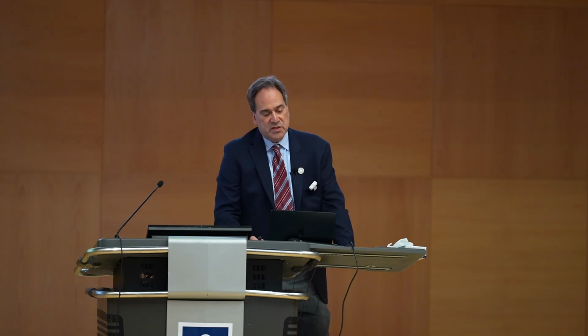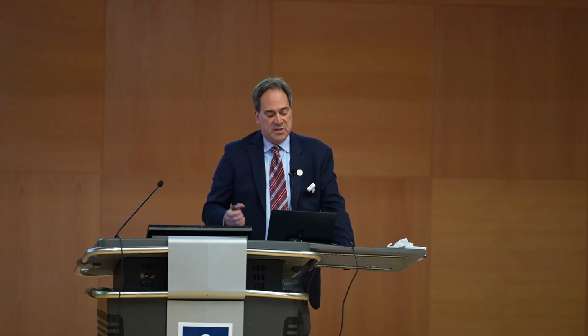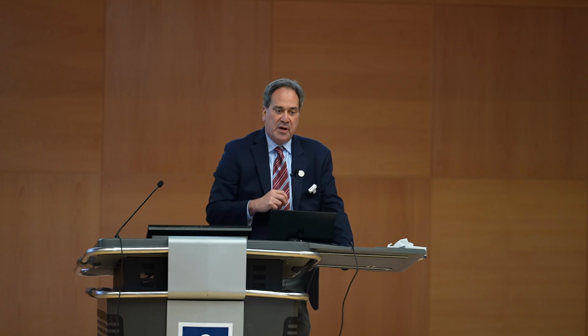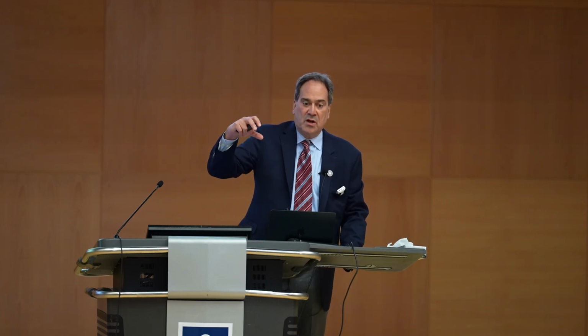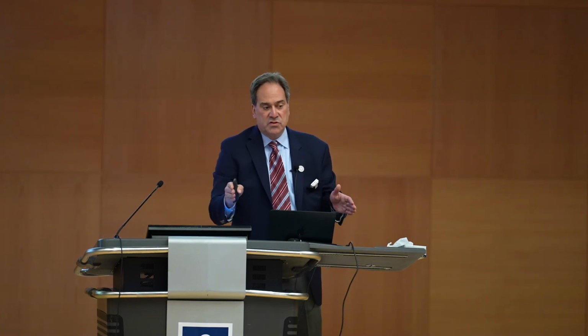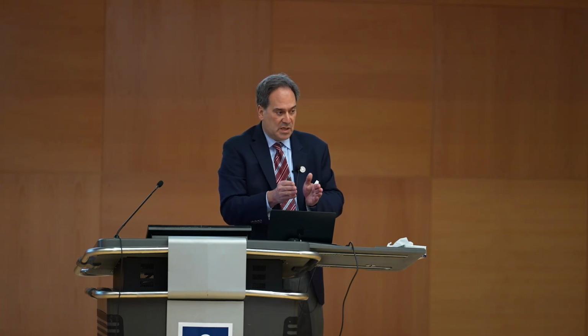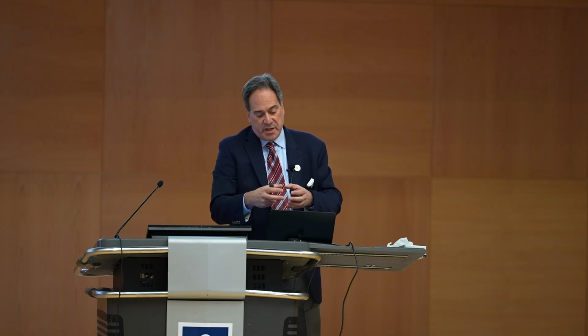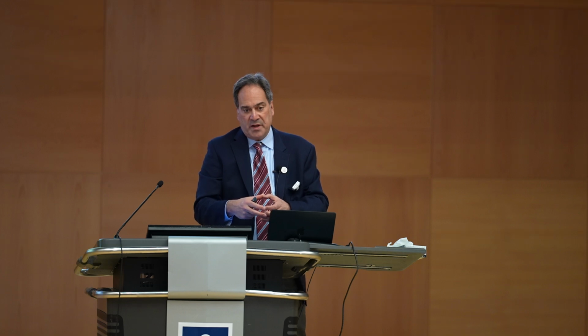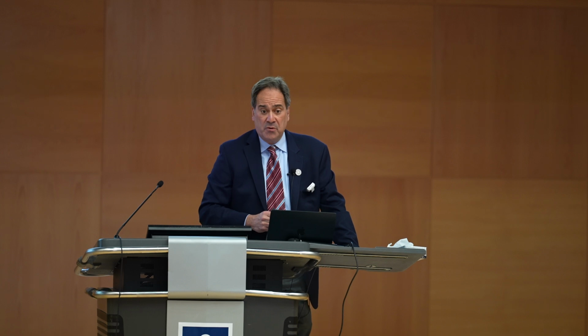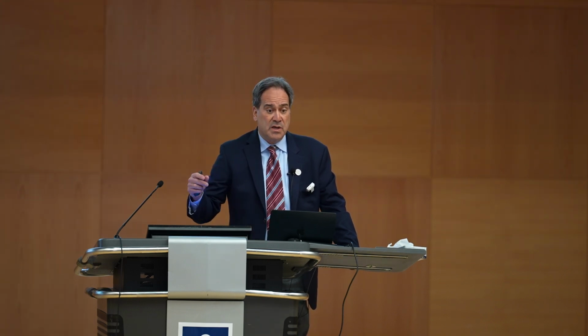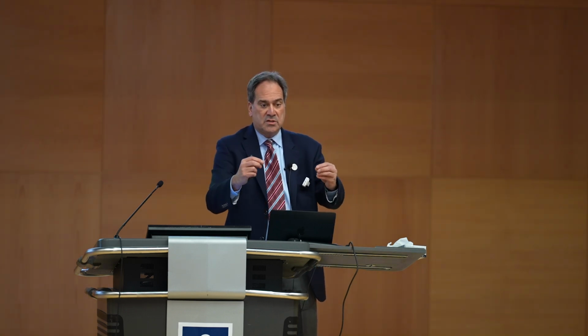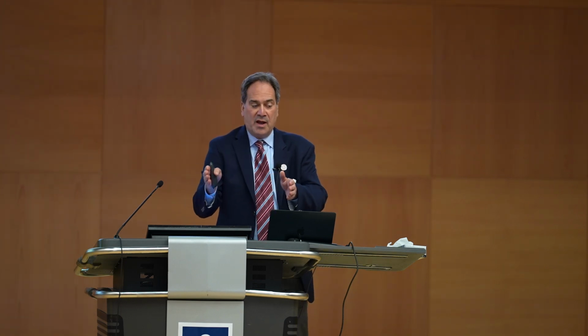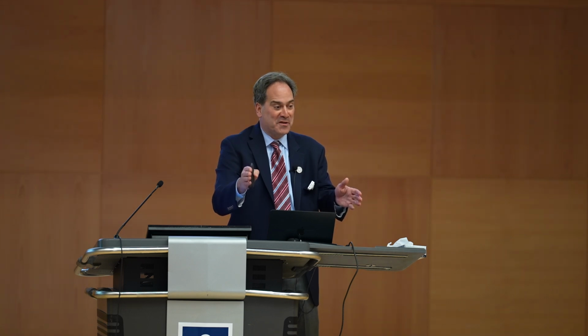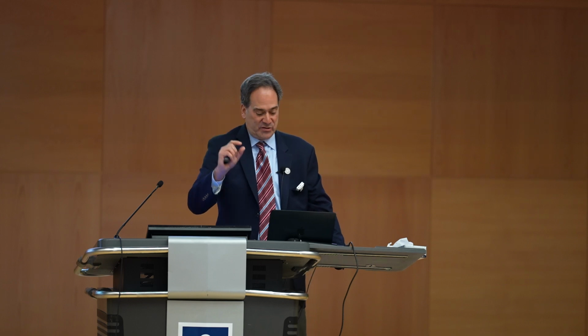So we came along and we said we could use these tools, these scanning probe tools, and block copolymers, in this case polyethylene oxide-poly-2-vinyl pyridine, loaded up with metal salts ahead of time, and we could use the tips to locally deposit blobs of material, polymeric blobs of material, onto a hydrophobic substrate. We call those nanoreactors. Those reactors are incredibly reproducible in terms of volume, size, dimensions. What that means is we can create a reactor that has almost a countable number of metal atoms within it. And then we can post-treat, thermally for example, under a reducing environment, blow away the polymer, reduce the metal atoms, and if all things work properly, all the atoms in that reactor will coalesce to form a single particle. To give you a feel for how small these are, they are attoliters to yoctoliters. You can look up those prefixes in terms of volume. These are tiny, tiny reactors.